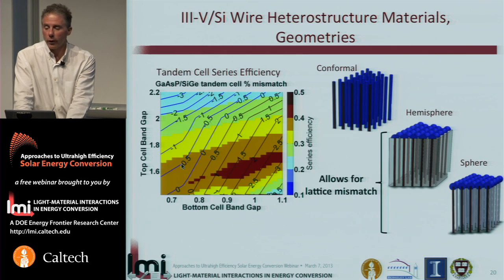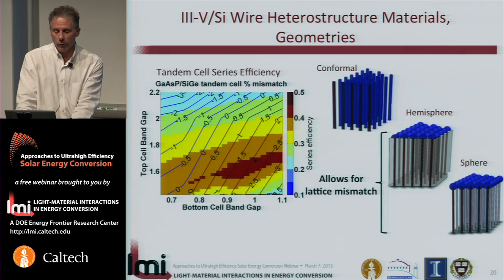In order to achieve efficiencies that are well in excess of silicon photovoltaic efficiencies, it's going to be necessary to think about going beyond silicon as an absorber material. And we've been thinking about how this might be done by integrating compound semiconductor materials, compound semiconductors in the III-V compound family, either by conformal growth or by selective epitaxial growth integrated with these silicon microwires. And by proper combination of the band gaps of the top and bottom cell materials, it's possible to substantially increase the efficiencies.